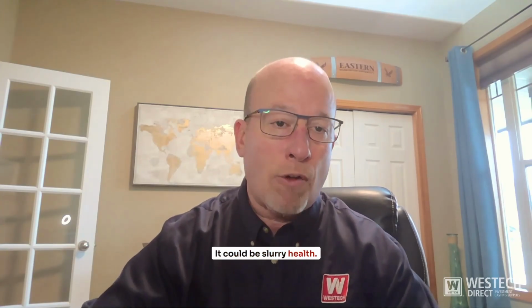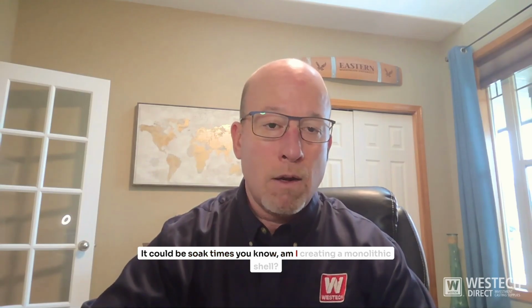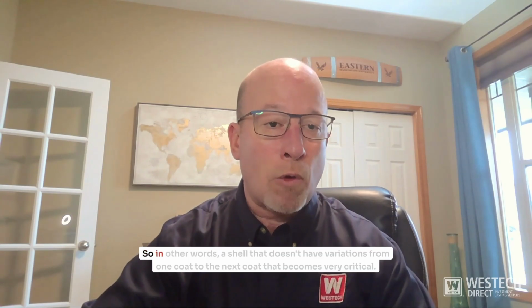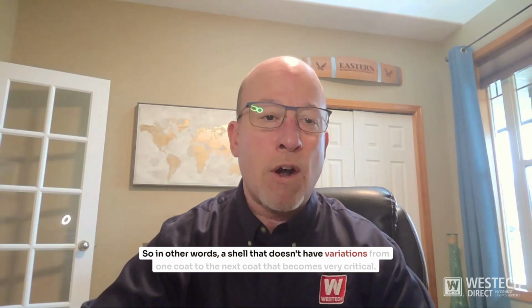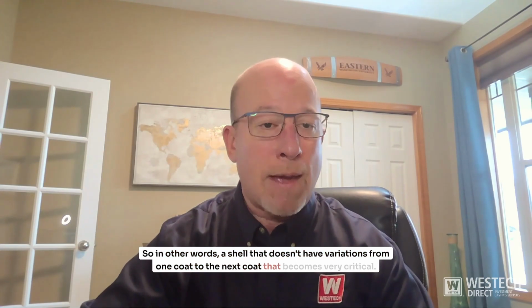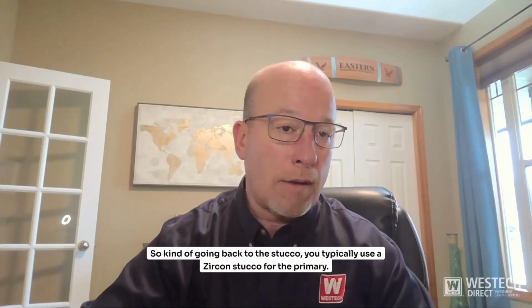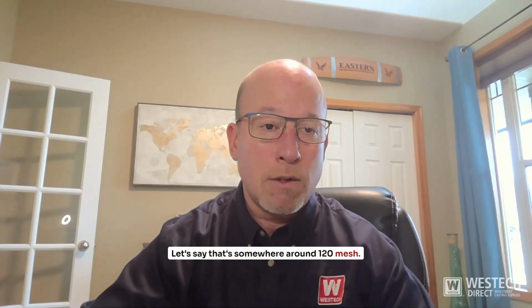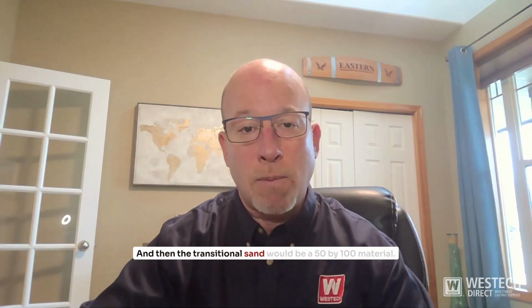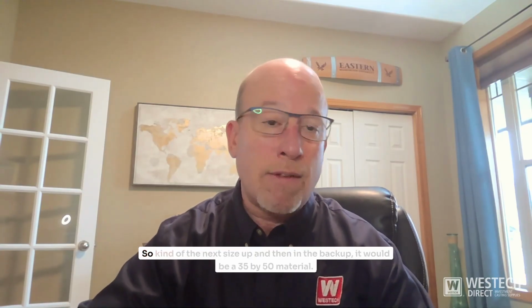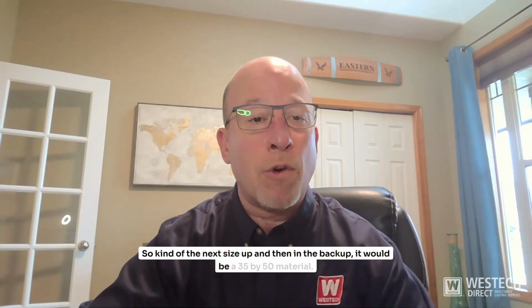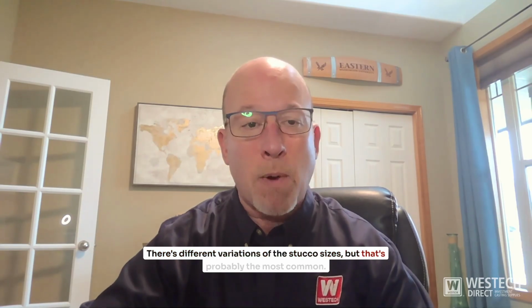It could be slurry health. It could be soak times. Am I creating a monolithic shell? In other words, a shell that doesn't have variations from one coat to the next coat. That becomes very critical. And once again, that transitional sand really helps. So kind of going back to the stucco, typically you use a Zircon stucco for the primary, let's say somewhere around 120 mesh. And then the transitional sand would be a 50 by 100 material, so kind of the next size up, and then in the backup, it would be a 35 by 50 material. There's different variations of the stucco sizes, but that's probably the most common.